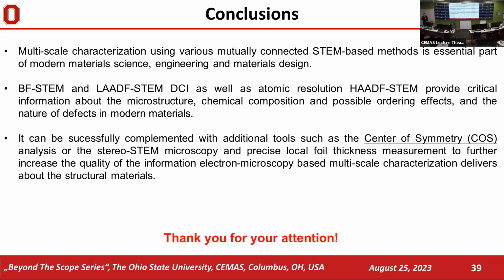So yeah, nice discussion. If I may have one comment from a practical user point of view: if you do defect studies, it's always a very thin balance between thickness and the area you're trying to study. If it's really thick, then the diffraction contrast at lower magnifications is nice and easy, and the defects are nicely resolvable. But as you get to thinner and thinner areas, you're getting other effects, like the surface effects of the foil. And then the question is, what happens with the dissociation of the partials? Are you getting a true representation of the defect structure you're looking for? So it's always tricky. Different alloys, different materials: what's the thickness to use for samples to get the answer you're looking for?